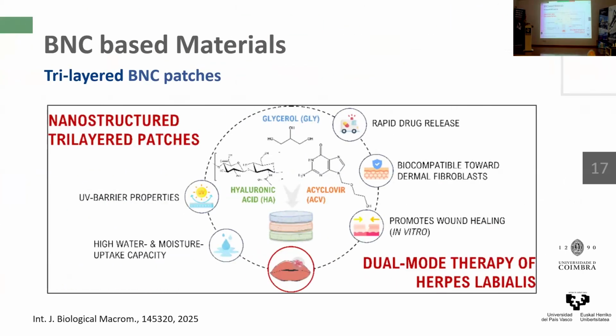More recently, we decided to prepare multi-layered systems, but using only bacterial cellulose. So we only use these bacterial cellulose membranes, and here the objective was to produce a multifunctional patch that can be used in the treatment of herpes labialis. And we achieved this by using acyclovir, that is a common drug used for the treatment of this disease, and also hyaluronic acid, that is a biopolymer widely used for skin regeneration. And we are able to get other important properties.